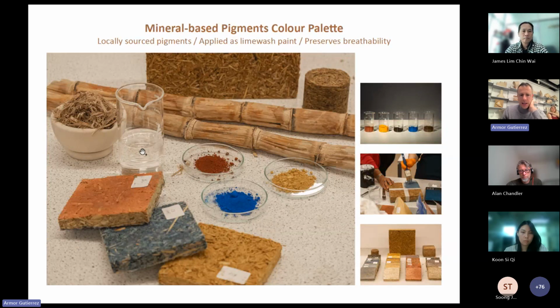This is the silica base binder that we use for the mix. These are the fibers of bagasse as they come, and this is the bagasse itself, dry, once you have cut it. Some samples that we develop, the samples have different sizes depending on the testing that you are going to do. This is the testing that we do for reverberation at the laboratory, and this is the testing that we do for thermal that tell us what is the conductivity, the thermal conductivity of the material. And all these samples and all this testing was done as well as part of the construction workshop with the students.